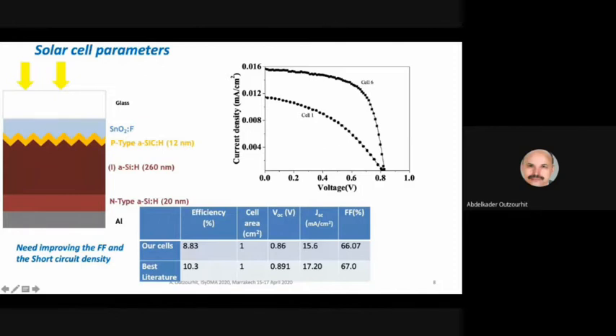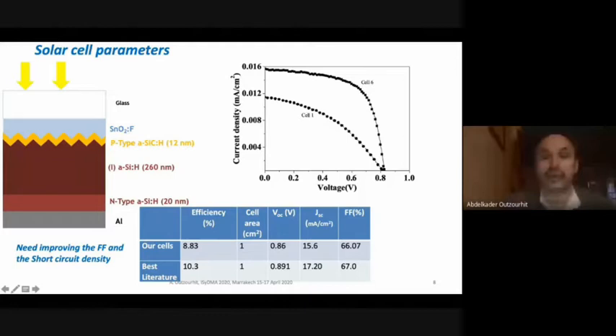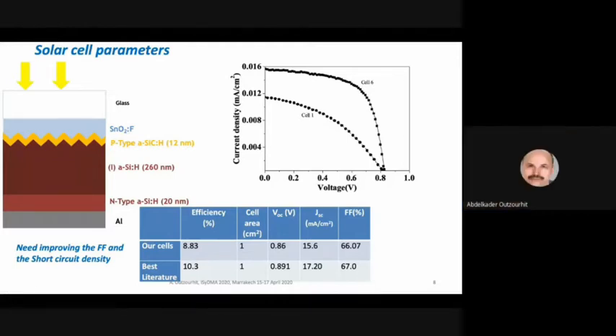This is a typical current versus voltage characteristic of the cells that were measured. I show here two cells, but the best cell that we have obtained so far shows an efficiency of about 8.83% with an open circuit voltage of 0.86 volts, a short circuit current of 15.6 milliamps per square centimeter, and a fill factor of about 66%.